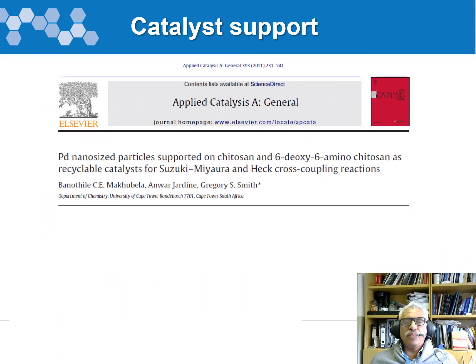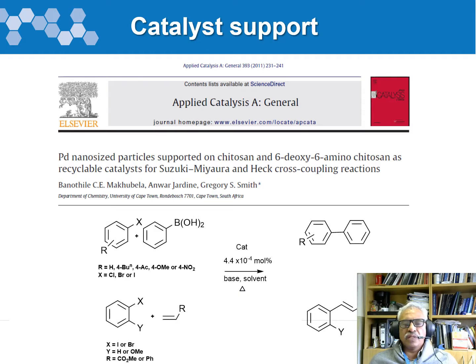So as a catalyst support, we published a palladium supported catalyst. And this catalyst could do Suzuki, Miyaura, and Heck cross-coupling reactions in aqueous or alcoholic water mixtures. And also the catalyst was much more stable as a heterogeneous catalyst compared to the equivalent homogeneous catalyst. And we could get really good yields and very good turnover numbers.